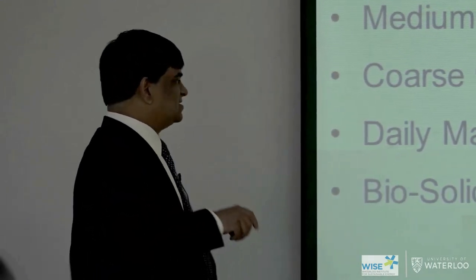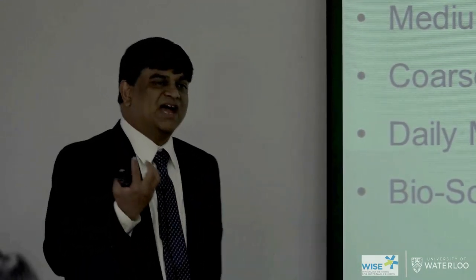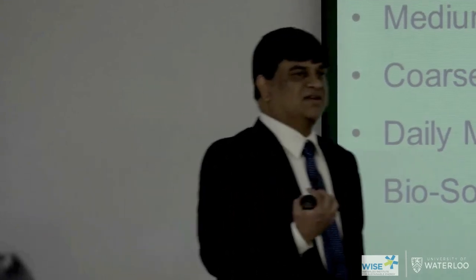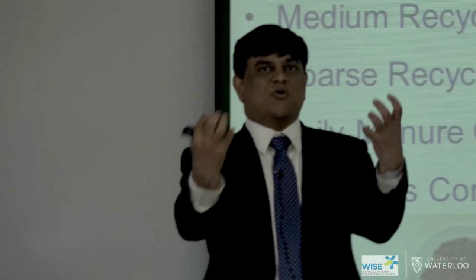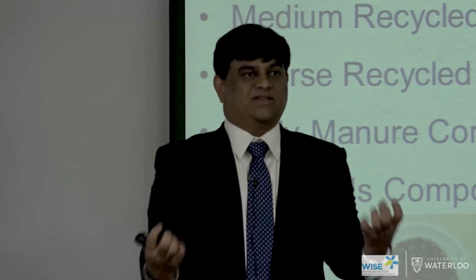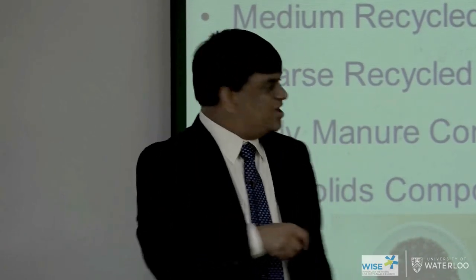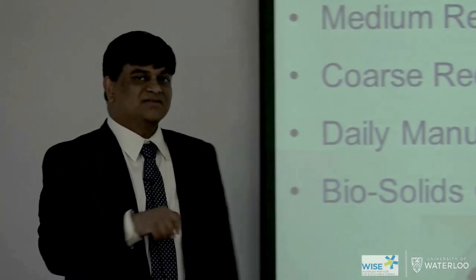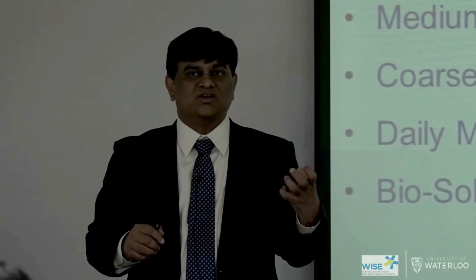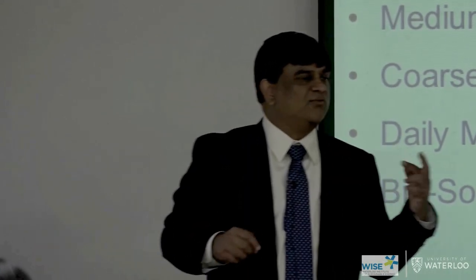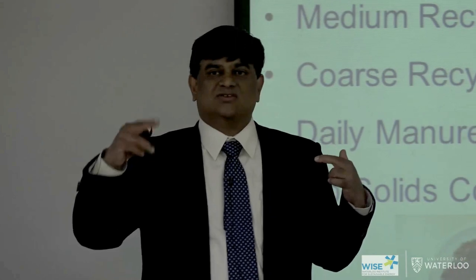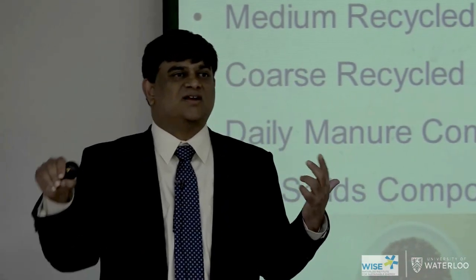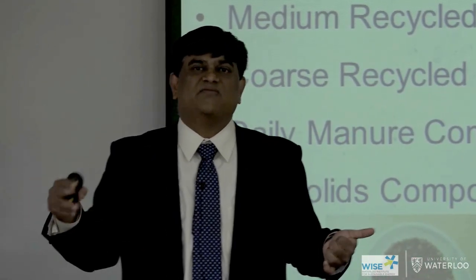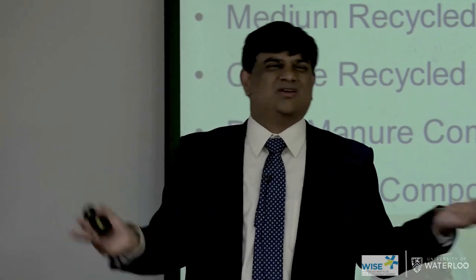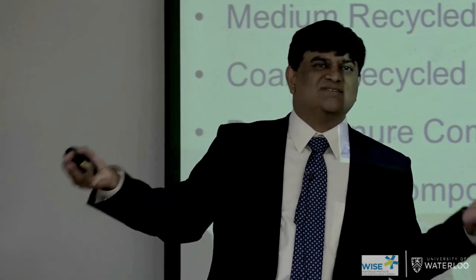The reason we did is these two materials have hydrophilic characteristics. Hydrophilic means that they absorb moisture from the atmosphere. So if you have a soil that has these materials, they absorb moisture. Believe it or not, you may get 1 or 2% moisture values. So if you have optimum moisture content of 14%, you may get 15 or 16%. Okay, so what? 14 to 16%, that's not a lot.